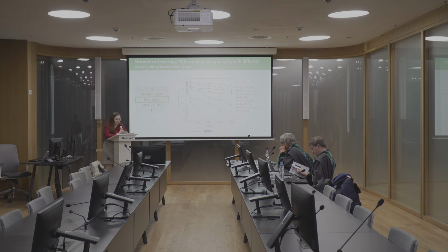If I remember correctly, figure D, which we refer to, also represents a single phase, but all these additional peaks actually come from the substrate that we used for the measurement. Yeah, but why did you not show that these are substrate peaks? Yes, that's my mistake, probably. But what was the main point for showing this Appendix A? Actually, the purity of the phase is mostly confirmed by this major peak, which occurs near 15 degrees 2 theta.